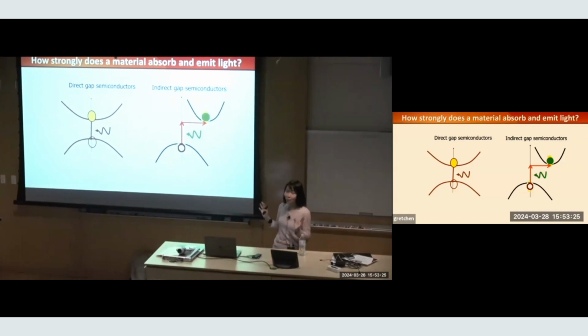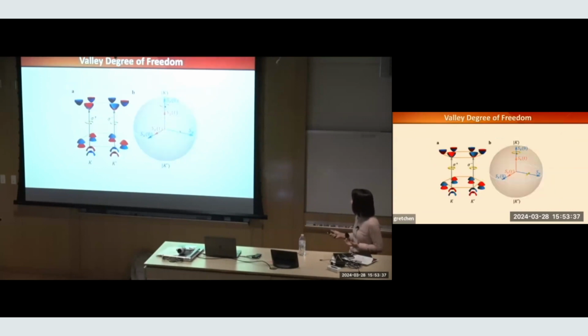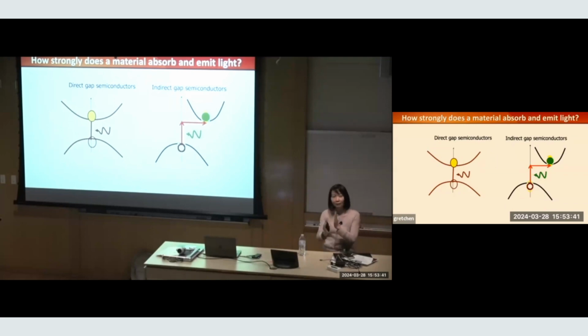But silicon, the most important semiconductor, of course, is used as detectors all the time. We still use them as detectors, but their efficiency would be better if they were made into a direct gap semiconductor. So what happened is actually between 2 layers and the single layer, the band structure made a transition from an indirect semiconductor to a direct semiconductor. And that's why light emission becomes 100 times more efficient in a monolayer than a bilayer. So that is really a dramatic example of quantum engineering, thinning down the material, changing the possible energy states electrons can occupy, changing the band structure, making the material go from an inefficient light emitter to an efficient light emitter. Right? It's following a long line of strategy using quantum confinement to change properties of materials. Right? So this is a wonderful example of being able to do that.